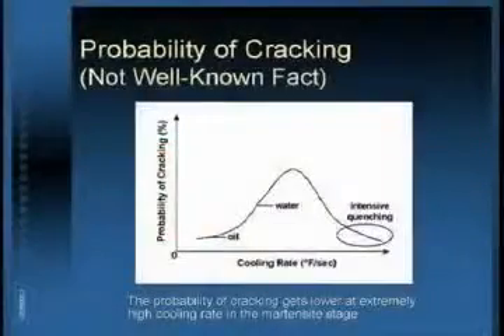Therefore, heat treaters have always struggled for a balance between a high quench rate for its better part properties or a lower quench rate to reduce the probability of part distortion or cracking. The intensive quenching theory and practice proves that this curve is actually a bell-shaped curve.